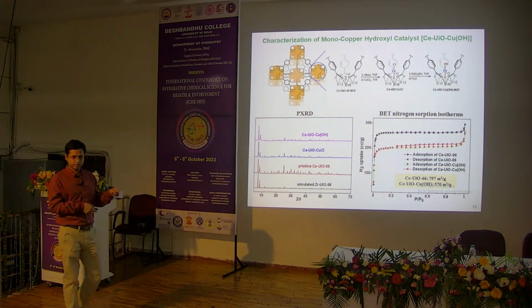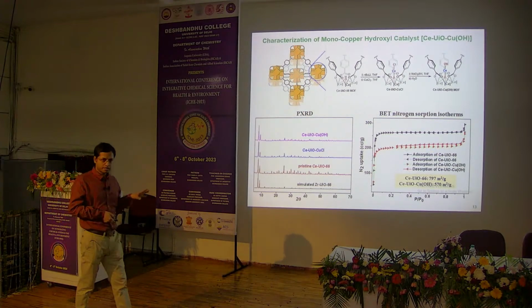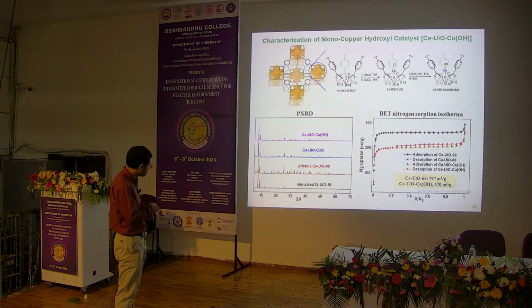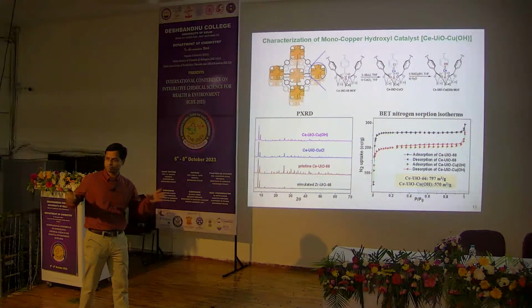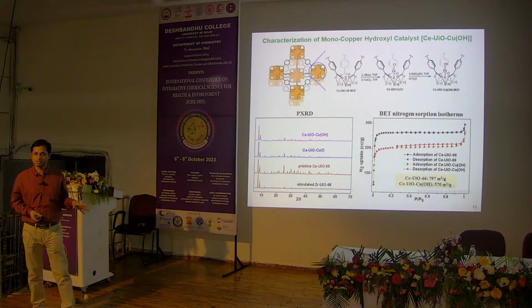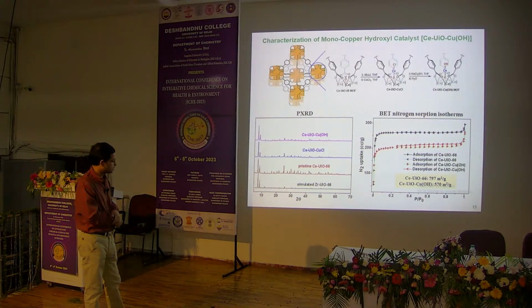So this is the characterization. The structure of the MOF is characterized by powder XRD. This is the simulated powder XRD from the UiO MOF. We can see the similarity of the powder XRD patterns of the pristine MOF and the metallated MOF. It indicates that the MOF structure remains the same. It is crystalline and it has a UiO structure also.